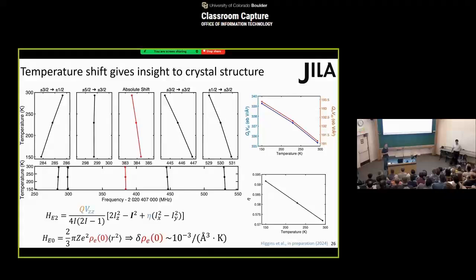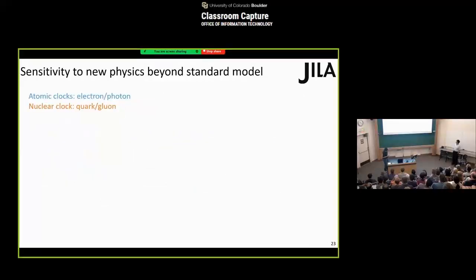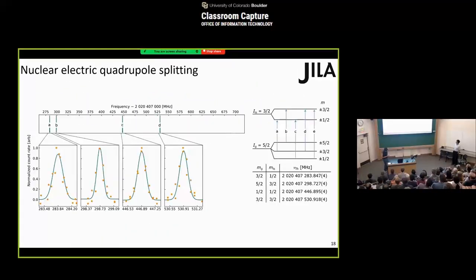Okay. And the other question is, what's the picture of these different states? Is that well understood from nuclear physics, the different levels that you're interrogating? Like, should I just think of it as a liquid droplet with different configurations? So these are the nuclear states. Yeah, so these are essentially just the different alignment of the quadrupole moment with respect to the local electric field gradient. This is not an internal nuclear structure, but since we probe the nuclear transition inside the crystal, we also see line splittings through this interaction.